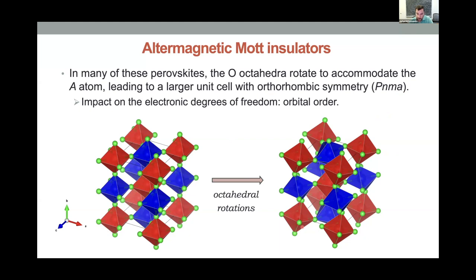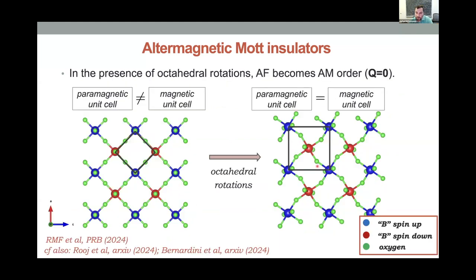And especially what happens now, and I can walk you through that, is that the new unit cell, which is this one now, has spin up and spin down. And these atoms are actually not related by inversion, but are related by a screw axis, which corresponds to a rotation plus a half translation. Okay? So this is just to show that you have this interplay now, even in strongly correlated systems. Now, there's an extra ingredient in the Mott insulators because these oxygen octahedral rotations also impact the orbitals. And this, I think, is a point that's being explored.